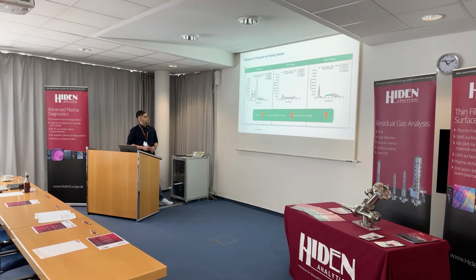In case of LF pulse, HF pulse, and sync pulse, for all of them, when we increase the pressure, the intensity at higher ion energy range decreases, and the intensity in the lower energy range increases. For all of the pulsing modes, this is the same.